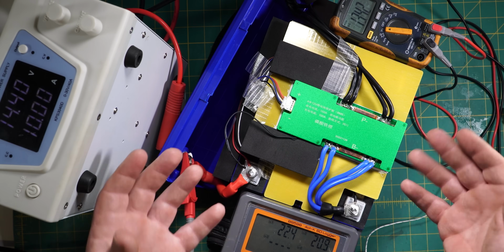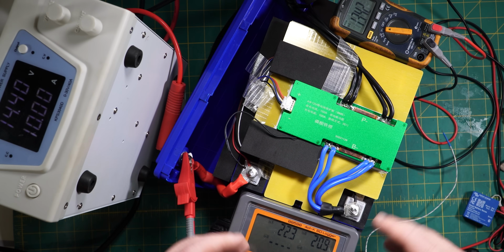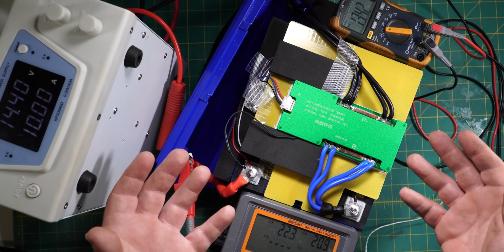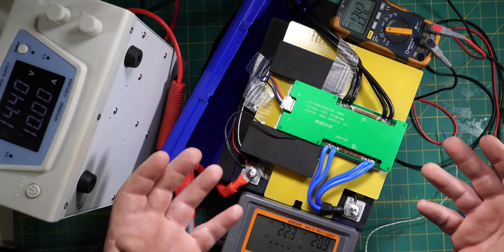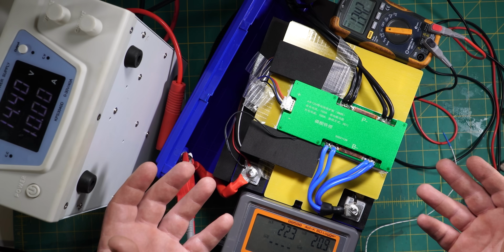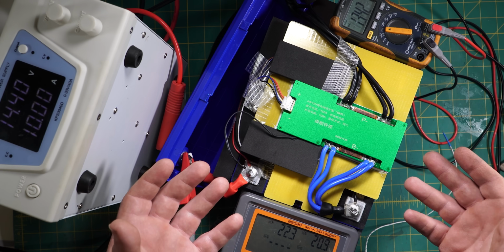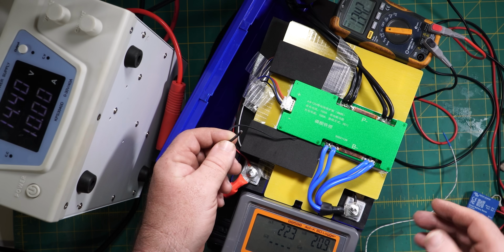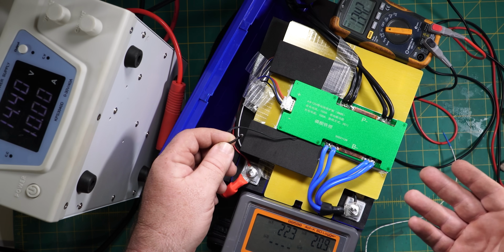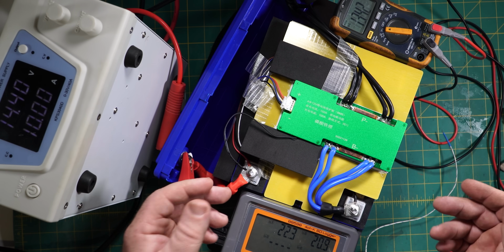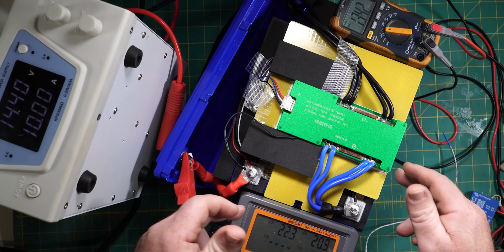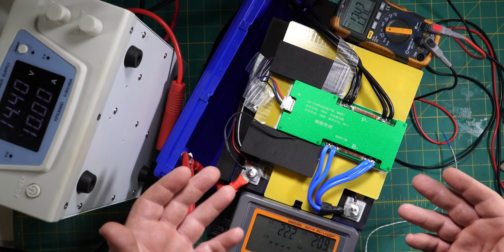So what are my final thoughts on this battery? Well, the performance testing it passed with flying colours, and the hot temperature testing, both charge and discharge, also passed with flying colours. But this temperature probe, when it was down to negative 10 degrees Celsius, was still allowing me to put energy into these cells, and frankly, that would have killed the battery.